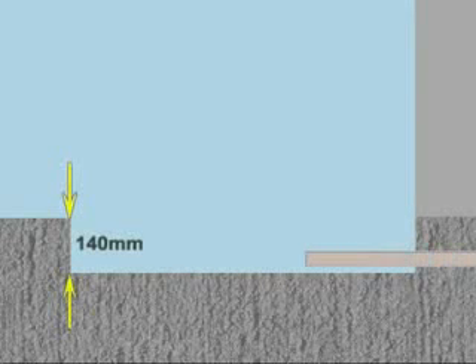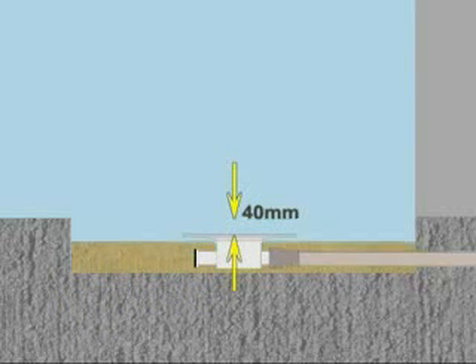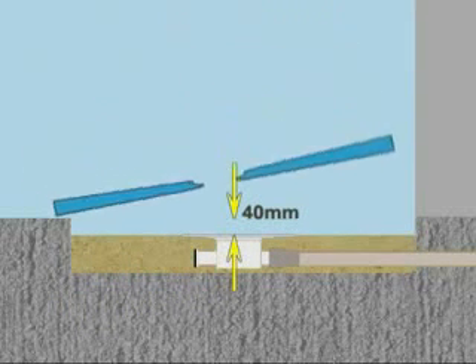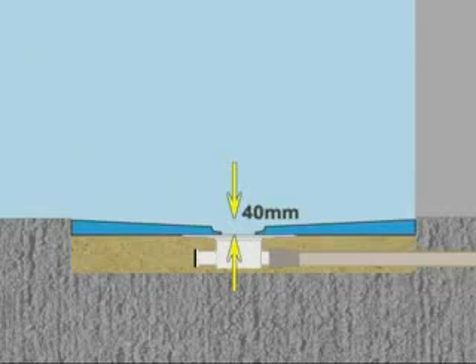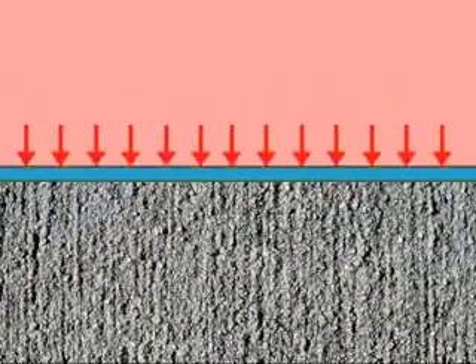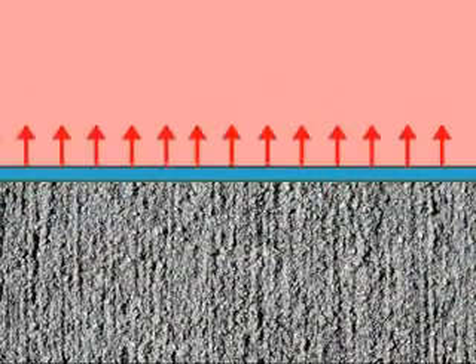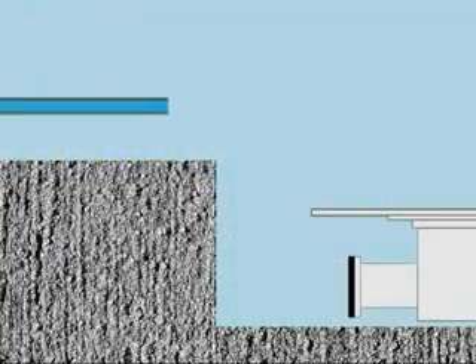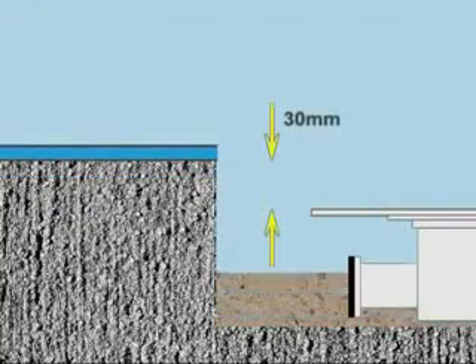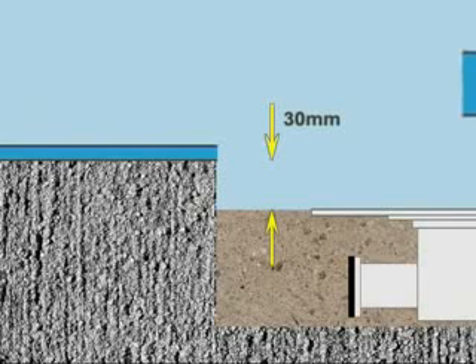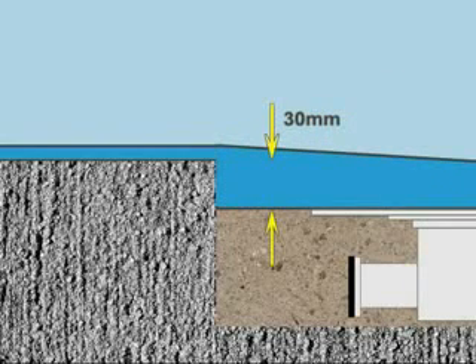If you were installing Fundo in a solid floor, you would first create a void in which to place the drain and base. If you were going to make it flush with the slab surface, the top flange of the drain unit would need to be 40 mm below the floor to allow for the thickness of the Fundo. To improve the thermal performance of the floor, essentially making it feel a bit warmer underfoot, you would use 10 mm thick sheets of tile backer as a tiling substrate on the floor. In that case, you would make allowances by setting the Fundo 30 mm below the slab surface.